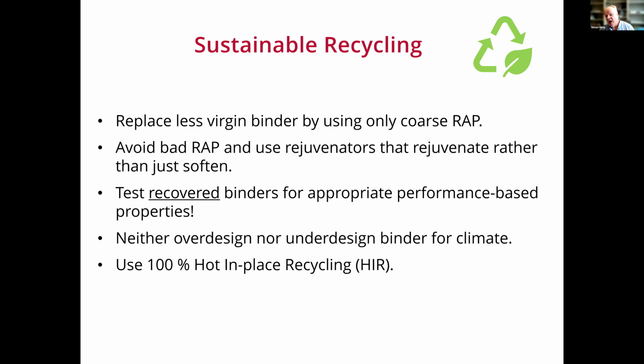And you should use hot-in-place recycling wherever you can, because that does not suffer from death by 1,000 cuts like central plant regular RAP recycling does. If you cannot do HIR and it is a bad quality RAP, just mill it into the subgrade, do full depth reclamation, and start over with the correct asphalt binder. And then 30, 40 years later, you may be able to do hot in place.